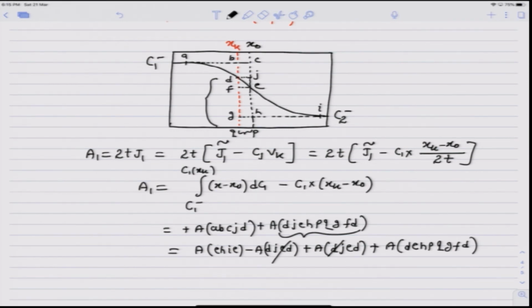if I mark this area, the shaded total area is nothing but the cumulative intrinsic diffusion flux A1 of component 1. This is basically the total amount of component 1 which has crossed this marker plane in time t. This is Heumann's method to find cumulative intrinsic diffusion fluxes.